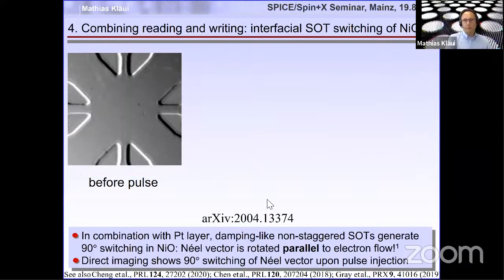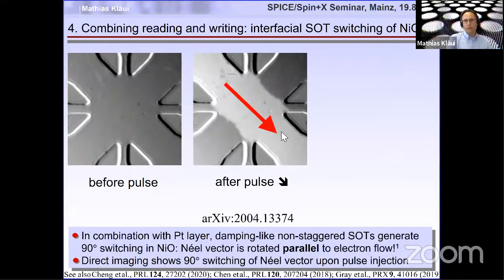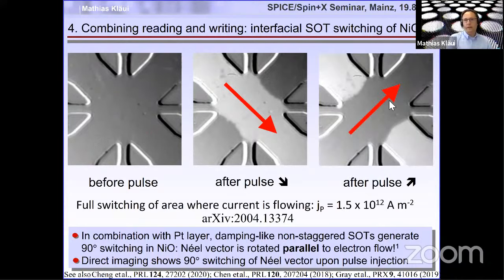This was done in this work here by Felix Schreiber et al., where we started with a Hall cross, as shown here, and we inject a single current pulse, and we can switch the magnetization in this cross, the Néel vector direction. Then we can inject a current pulse with a 90 degree different direction, and we see we switch it in a 90 degree different direction. So firstly, there's direct imaging of the Néel order reorientation, meaning that indeed we can see a 90 degree change of Néel order, so it's a magnetic switching.